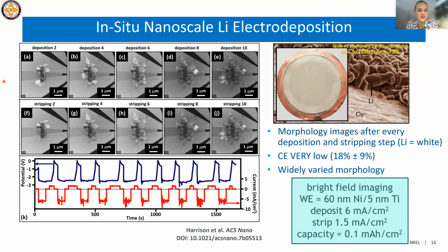Okay, so getting back into this electrolyte, this is work with Dr. Katie Harrison, and what we found was that through cycling in this electrolyte, we weren't actually seeing a difference in the lithium morphology that we expected to see from the PNNL paper. And so we had very low coulombic efficiency, and the morphology was still high aspect ratio lithium grains, not these big, dense lithium grains that we were expecting to see.